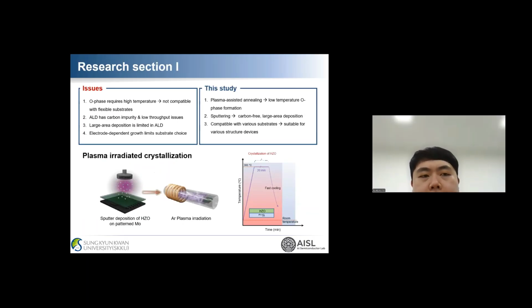As mentioned earlier, hafnia-based ferroelectrics are promising materials for next generation electronics. Among them, HZO, hafnium zirconium oxide, which is a 1-to-1 ratio mixture of hafnium and zirconium, has attracted significant attention. Compared to pure hafnia, HZO shows ferroelectricity at lower crystallization temperatures and exhibits improved ferroelectric properties. However, HZO still requires high temperature processing to achieve ferroelectricity, and its stabilization often depends on specific electrode condition. In addition, ALD processes have limitations such as carbon impurity, long process time, and difficulty in large area deposition.